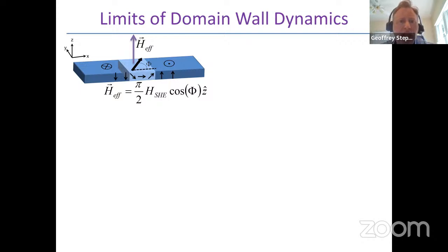When you apply either a spin current or a magnetic field that would drive that wall, the torque doesn't displace the wall, but the torque instead drives the domain wall from being Néel to being more and more Bloch. There's then a restoring torque inside of the domain wall, and it's that restoring torque that propels the domain wall forward. So it's really an indirect drive when you're driving a texture. The magnetic field or the spin orbit torque will cause a distortion of the wall. And the internal restoring torque is what then propels that domain wall forward.